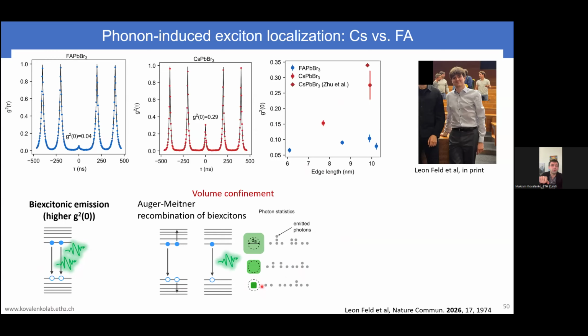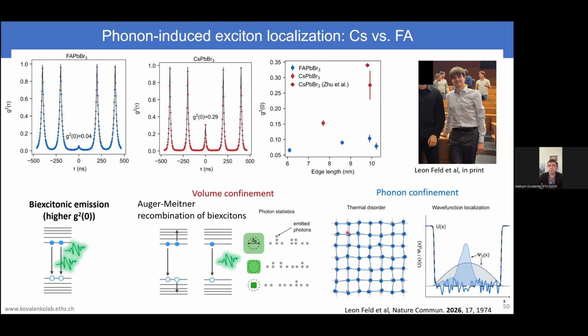But then they are very unstable, and that's a trade-off you can never solve. Now, with our quantum dots, we can break these of hybrid composition, formamidinium, not cesium. We break this sort of volumetric dependency, and Leon came up with a beautiful hypothesis that now not the physical dimension which matters for the Auger-Meitner recombination of biexciton, but it's actually local wave function localization which at elevated temperatures like room temperature originates actually from that lattice sort of dynamics.